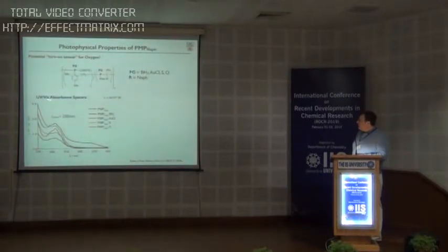And we can measure the spectra now of these polymers, and these are the absorption spectra, they don't look a lot different. We functionalized the polymer with different electrophiles through binding to the phosphorus atoms, so borane, gold, sulfur, oxygen. And you can see that all the functionalized ones are flat out here. The other one has a little bump. That's the transition from the lone pair of phosphorus. Now the chromophore, of course, is responsible for these bands.